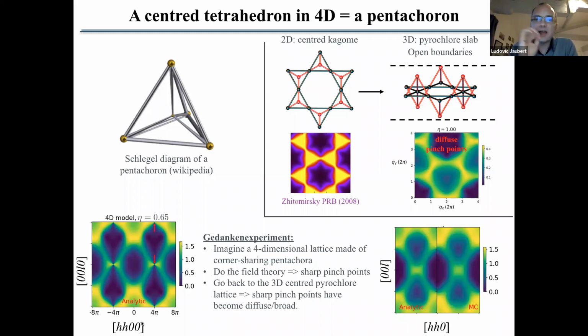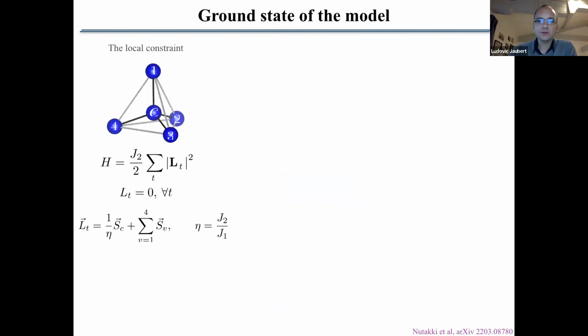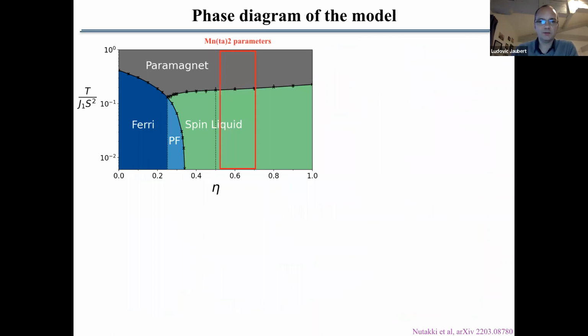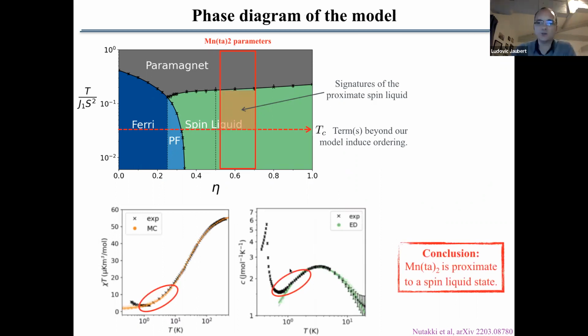No, I agree, and I should apologize because I was not careful enough in my wording. Here, in this regime, we still expect things to be classical. It's S = 5/2, so we still expect things to be classical here. This region is a region of moderately strong correlations. So the paramagnet is basically coming from spin fluctuations due to geometry, right? I mean, nothing to do with fractionalized excitations, the quantum entanglement people claim in the spin-1/2 system. Exactly. No, I do not expect quantum fractionalization, and I do not expect quantum entanglement, or at least nothing strong, nothing major there, because for this spin S squared.